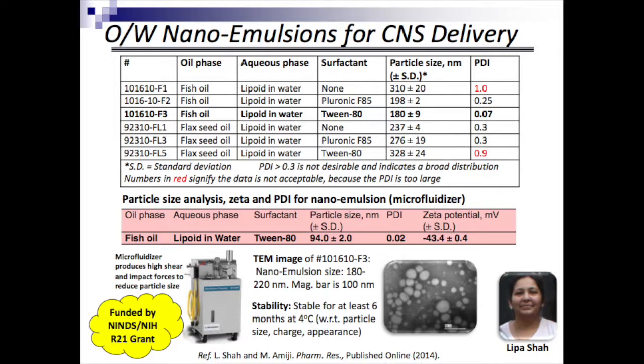The first approach that you see up here is designing the emulsions using an ultrasound approach in the lab, which can generate small volumes, up to about 5 ml to 10 ml. So for lab scale, we use this ultrasound approach, basically using an ultrasound sonicator, and we can reduce the oil particle size down to between 100 and 300 nanometers, depending on formulation. There are three components in an emulsion. It's a very versatile system.